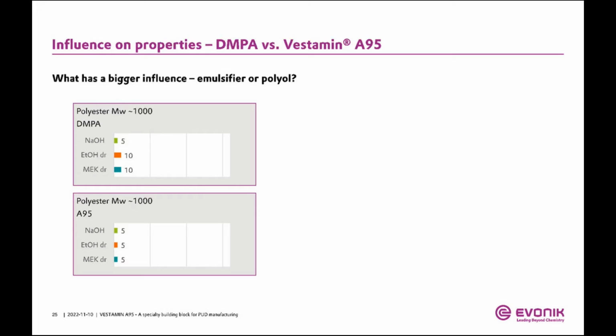So when we now talk about properties and how to influence them, the final question: what has the bigger influence? Your emulsifier or your polyol? And this is one thing I really want to point out. This is now another formulation, not really directly comparable with the examples you saw in the last slide. We now have a purely soft formulation, no hard segments at all anymore. And we take this polyester we talked about earlier with the molecular weight around 1000. We have relatively poor resistance both in the DMPA and the A95 case, even a little bit lower with the A95.